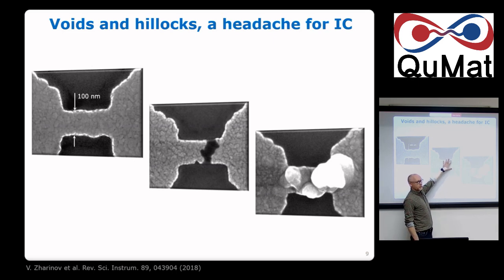So if you have that, your circuit does not work anymore. If you have that, this might touch another layer and you have shorts, so it doesn't work anymore. And that's actually what happened at the very beginning of this problem, because how easily you move an atom has to do with the binding energy, and the binding energy is proportional to the melting temperature.